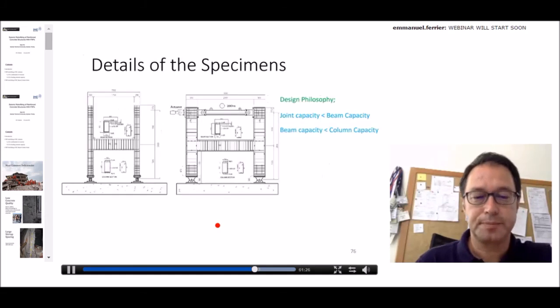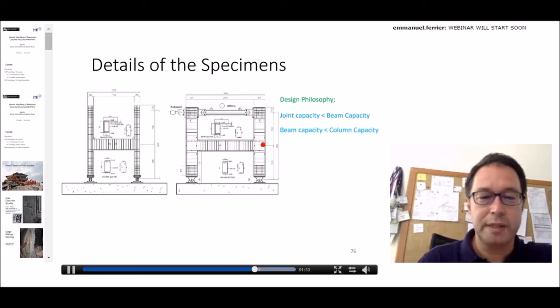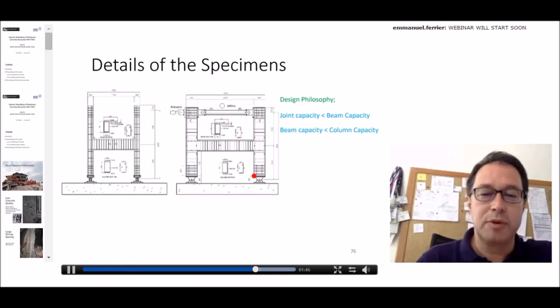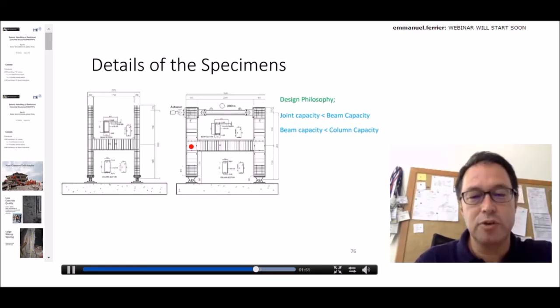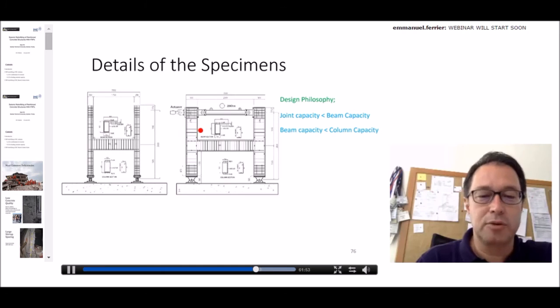This is showing the details. As you see, again, there are no transverse reinforcing bars within the joint. Again, the strength hierarchy was similar. The most problematic areas were intentionally the joints, and then the beams, and the columns were stronger. So we expected damages first in the joint, and if you retrofit the joints, the damages are expected to occur within the beams rather than the columns.